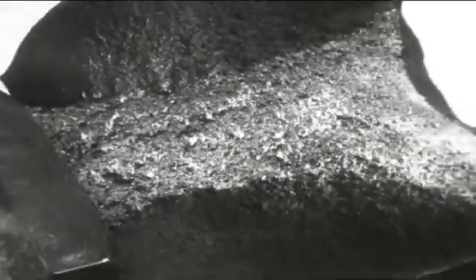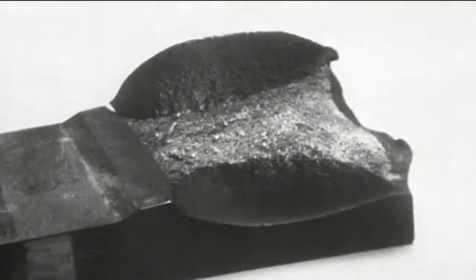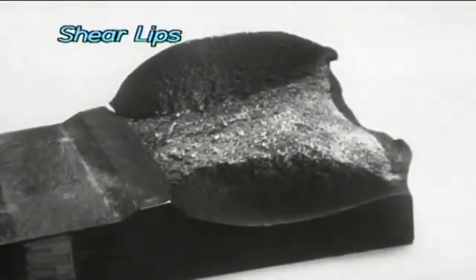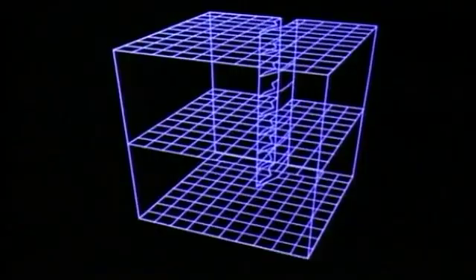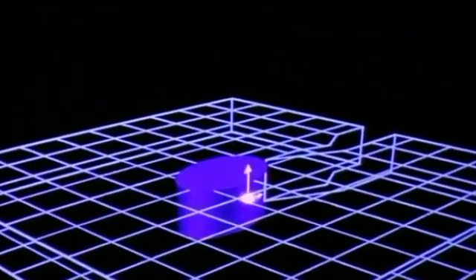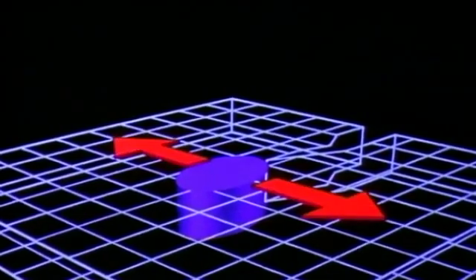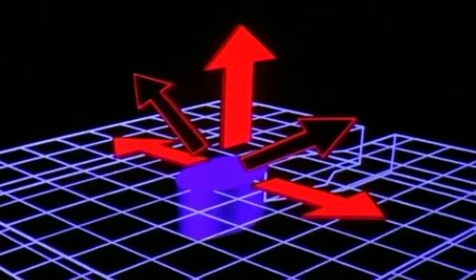This changes when we move towards the edge of the specimen. The fracture is no longer flat, but shows these shear lips. To understand why, it's easiest to consider first a thin specimen, where the plastic zone is big compared with the specimen thickness. Virtually the whole of the plastic zone is outside the plane strain region. The maximum stress is the same as for the thick specimen, in the direction of the applied stress. But now, the minimum stress is 0 and perpendicular to the surface. The direction of maximum shear is therefore at 45 degrees to the surface.